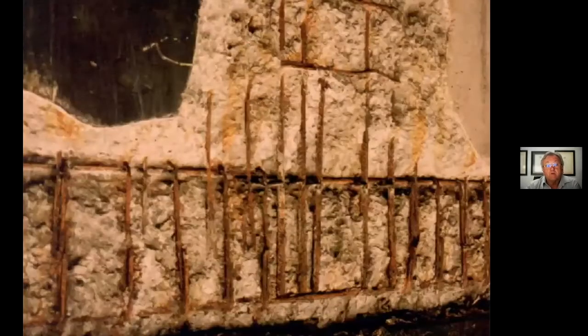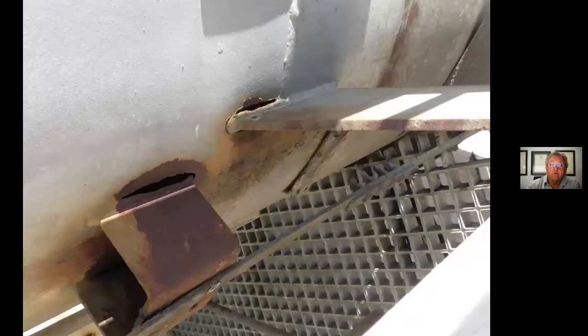Here's an example of a situation where a structure was designed for a particular environment, and due to fallout from an adjacent process, the structure was contaminated with highly aggressive salts, and the net result was serious corrosion of the reinforcing. Here's an interesting example of a chimney on a boiler.